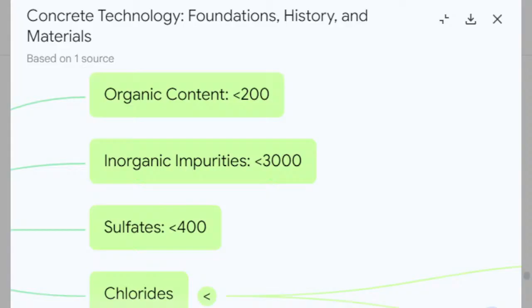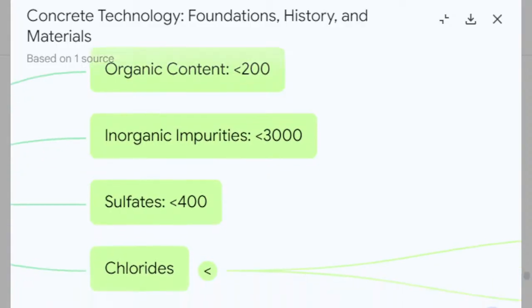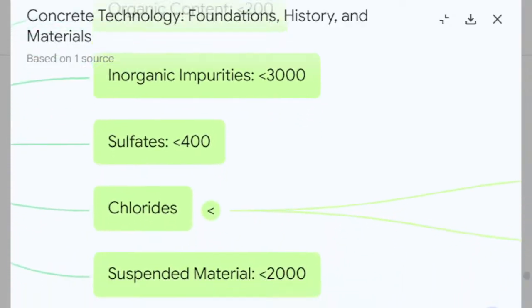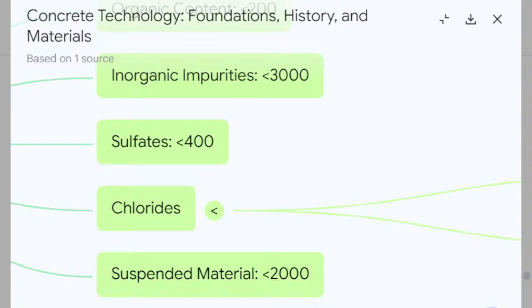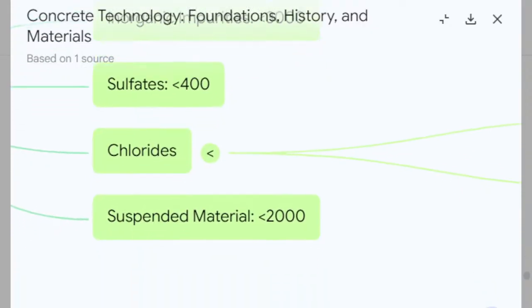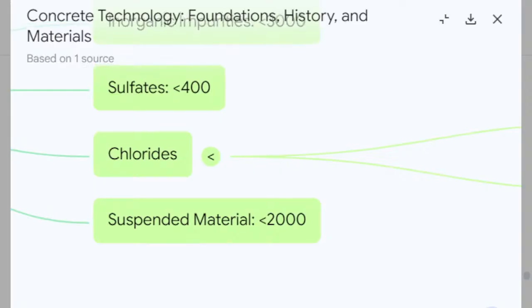Inorganic impurities. These are general dissolved salts and inert particles. There's a broader limit here, maybe around 3,000 mg/L. Too much can just dilute the mix and affect workability. Sulfates. These have a tight limit, often around 400 mg/L. Higher levels are extremely problematic. Sulfates can react chemically with compounds in the hardened cement paste, primarily calcium hydroxide and calcium aluminate hydrates, to form expansive products like ettringite. This reaction causes the concrete to swell internally, leading to cracking, spalling, and eventually disintegration. It's known as sulfate attack, a serious durability issue.